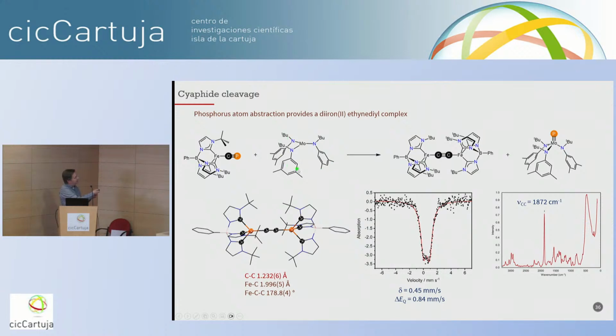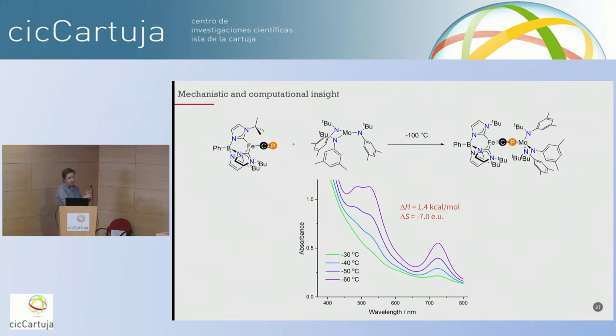But when we take this three-coordinate moly compound with our cyaphide compound, the first thing we were able to figure out that we made was the moly phosphide. And then eventually we were able to crystallize out this C2 complex, so this iron-bridged diacetylide complex here. So we again have a crystal structure, we have the Mossbauer, and then the Raman clearly shows we have a CC triple bond in this complex. So forming this suggests, well, obviously we have to break the CP bond, and you could imagine that you must be forming a transient carbide complex.